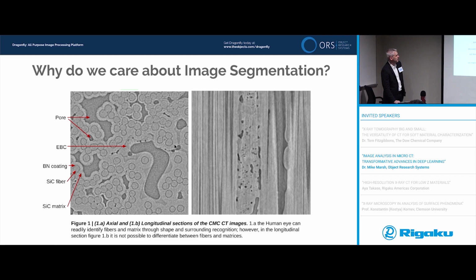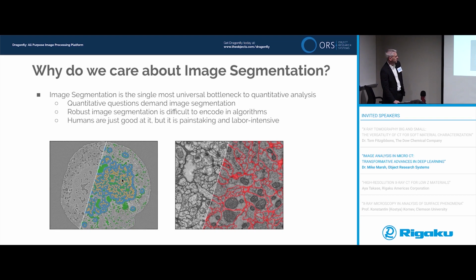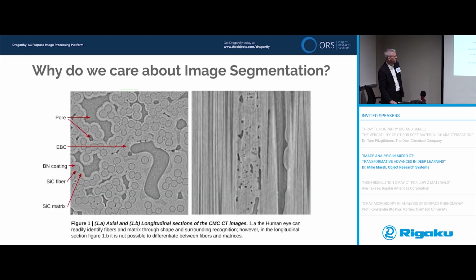Outside of this matrix is this material, which is called the environmental barrier coating. And in this image, it's what's out here that's not colored. There's some infiltrating in here, but most of it's what's outside of here that's not colored. The takeaway here is the environmental barrier coating, the silicon carbide fiber, the silicon carbide matrix, they're all either like 13 or 14 on the periodic table. They're all aluminum or silicon, and so they have almost no intrinsic contrast.